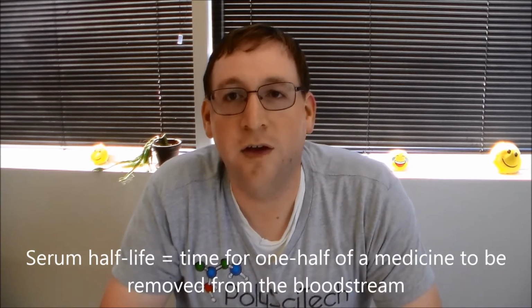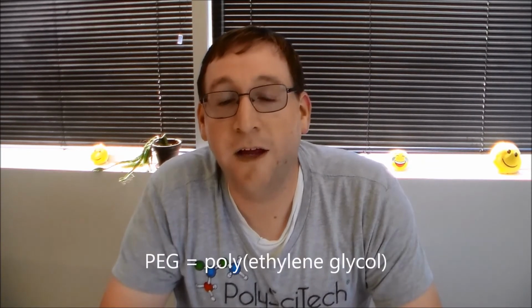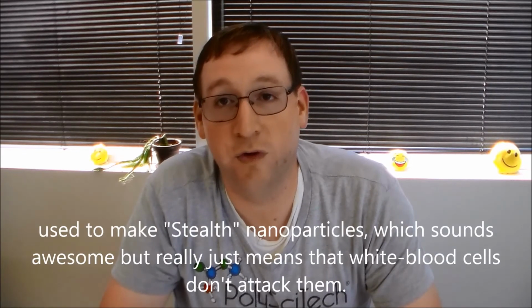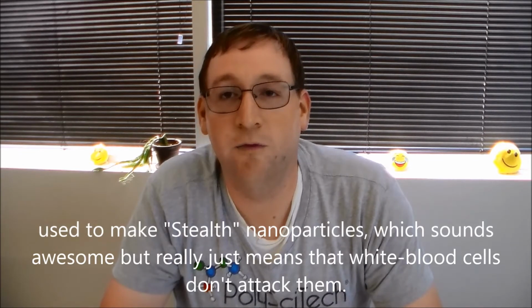Often you're dealing with molecules which are either poorly water soluble or are rapidly cleared out of the bloodstream, on the order of magnitude of even minutes sometimes. In this situation, there is an advantage to encapsulating that particular medicinal molecule inside of a nanoparticle so that it can last longer in the bloodstream. This is most notably affected when you apply a nanoparticle which has polyethylene glycol on the outside. Polyethylene glycol is a water-soluble polymer that does not elicit an immune response. One of the nice features behind it is, in fact, that it resists immune response, such that it prevents the drug and the nanoparticle itself from being cleared out of the bloodstream for a longer period of time than had it not been there.